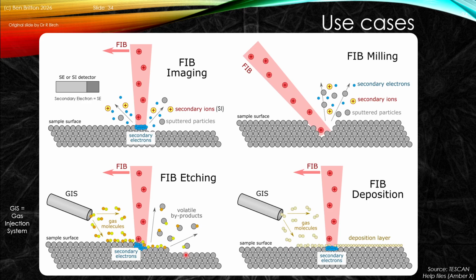When we've got the FIB, we can have a series of different use cases. We've seen this in a few places. We can do FIB-based imaging, where we use the incident FIB and we collect it with a secondary electron or secondary ion detector. And so we collect those ions or electrons, and we can measure the total interaction with our surface. This can give us topography and Z number, and also crystallographic contrast as shown.